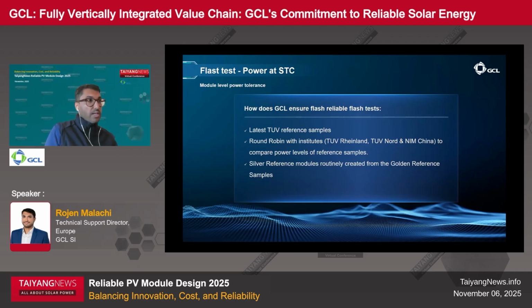GCL goes through a significant flasher calibration process. We maintain precise output calibration through round-robin referenced golden samples, tightly controlled flash test calibration, and also the power control bin. This reduces mismatch losses in projects and ensures delivered wattage meets or exceeds nameplate. So basically, you get what you paid for and not just theoretical numbers.